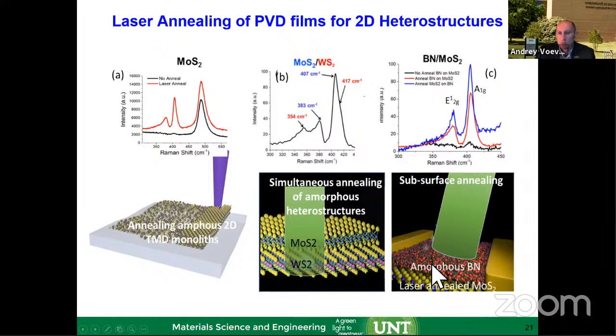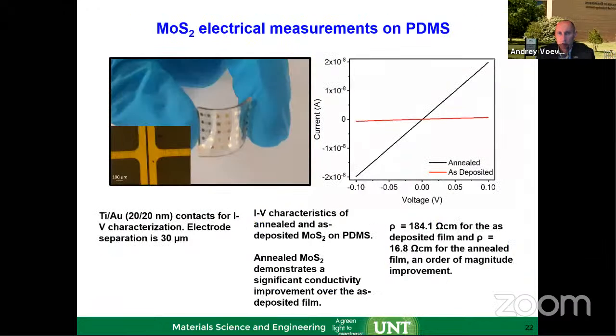You can also have boron nitride, which is a very good insulator dielectric material, and that leads to direct device fabrication. And because now you're not bounded by the temperature of the substrate, you can use a polymer substrate for the growth of these amorphous materials by sputtering and using laser annealing for a very short time, not damaging the polymer, optimized just to anneal it for the semiconducting channel.